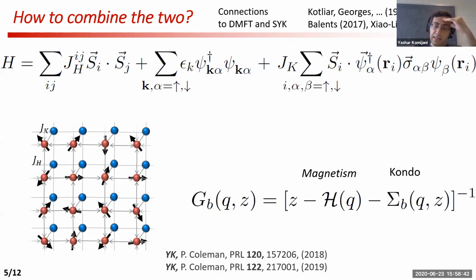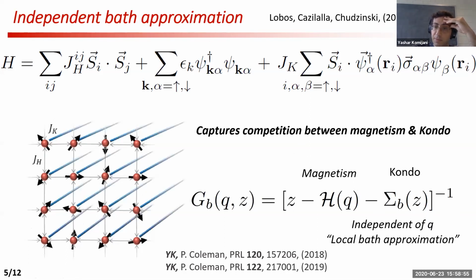A good starting point would be, as a first approximation, to discard the momentum dependence of the self energy. And this is what people usually do in single-site DMFT. If I replace this with a momentum independent self energy, it turns out that this is equivalent to a Kondo lattice where each spin is coupled to its own conduction bath. Admittedly, this is not sophisticated enough to capture all the complexity that we see in the materials or in the systems, but I would argue that this is a good starting point because it captures competition between magnetism and Kondo.